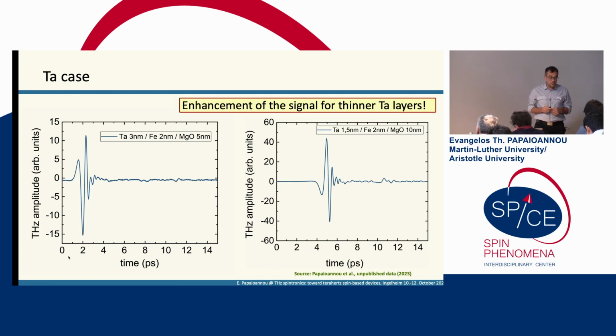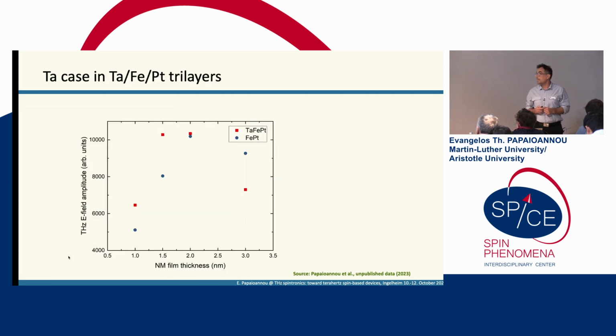This enhancement triggered us to go further and try to make the tri-layers. And here I compare in this graph the iron platinum bilayer with the tantalum iron platinum tri-layer, and on this axis you have the thicknesses of the non-magnetic layers. You see that the tri-layer is above for 1 and 1.5 nanometer. The 1.5 nanometer is the one that exhibits the highest signal I showed you before as a bilayer. At some point the terahertz amplitudes are comparable, and then it decreases.